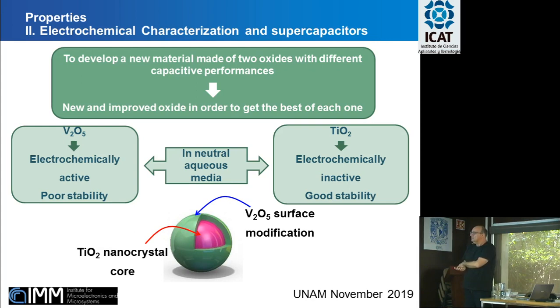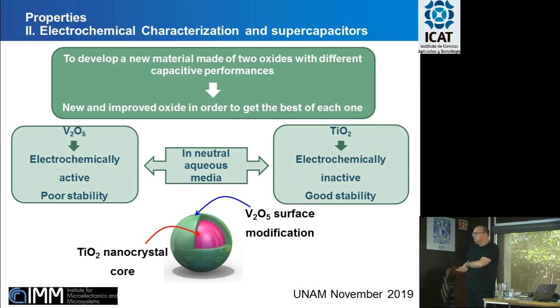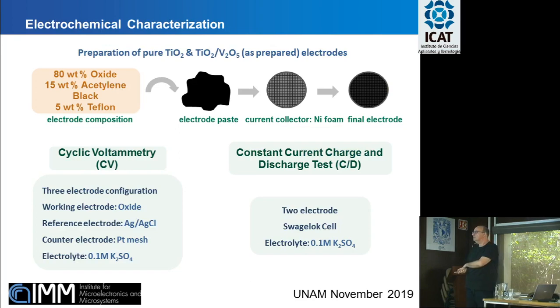Because vanadium by itself is electrochemically active but has poor stability. Titanium has a good stability and on the other hand is electrochemically in many conditions quite inactive. So the idea was to take the good things of the two materials by using this kind of core shell configuration. This is the device preparation.